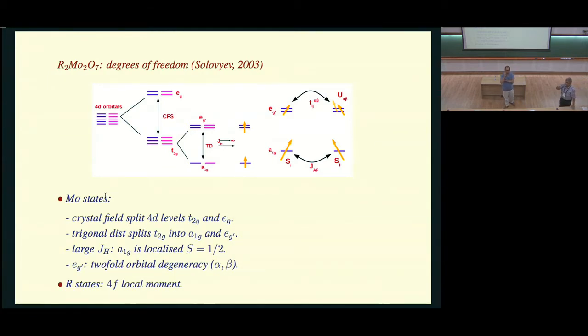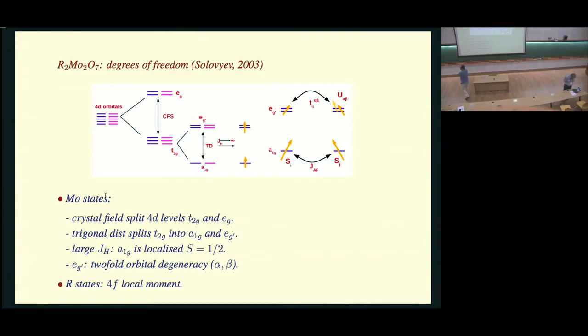Yes, Shubhra. Local moments, the rare earth local moments. Yes. So usually the rare earth local moments have not been brought into the story at all. The molybdate has a spin half. Wait, so what's happening to these rare earth local moments? Oh, the rare earth local moments are out of the story. They should be brought back. In fact, for some of the spin chirality issues, you need to bring back the rare earth local moments, which are weakly coupled to this magnetic subsystem, or so it is claimed.